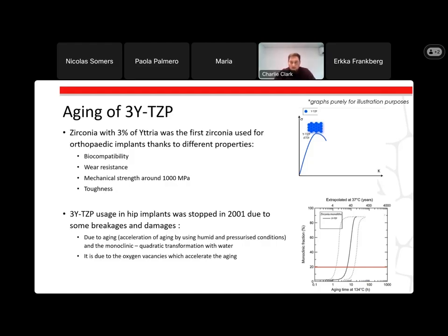So what we considered was that after 20% of monoclinic transformation, the part would need to be replaced. So as we can see here, when you extrapolate at 37 degrees Celsius, it means that the biomedical implant could last anywhere between 6 and 60 years, which obviously in biomedical terms is not great, because this means that the patient would be at risk of repeat surgery, which is what we're trying to avoid.